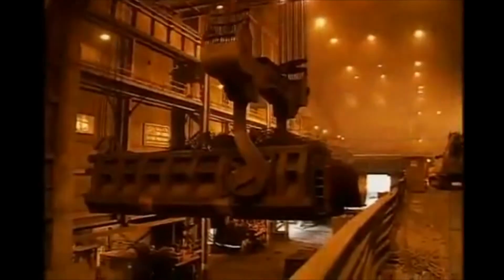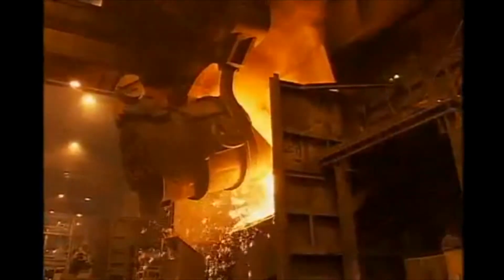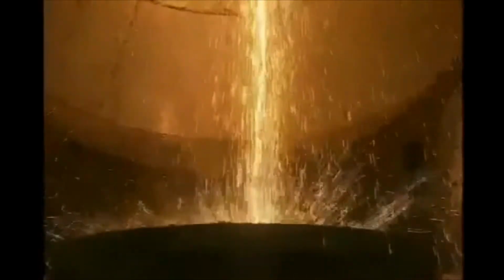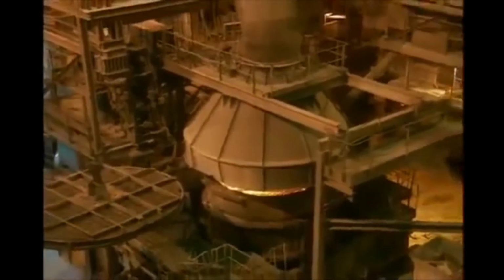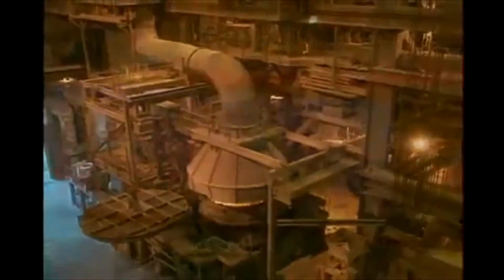We begin the steel-making process by dumping recycled steel scrap into the basic oxygen furnace and adding hot iron. Sparks steal the show when high-purity oxygen is blown into the mix at supersonic speeds and molten iron becomes molten steel. Now we're ready to create the custom blends that make steel the most widely used metal on the planet. In fact, we produce over 1,500 different chemistries to meet customer demand for cutting-edge, value-added steel. Look for another show of sparks as we tap molten steel from the BOP vessel into a ladle. Then, for most of our steels, it's on to the vacuum degasser, where they are made highly formable.